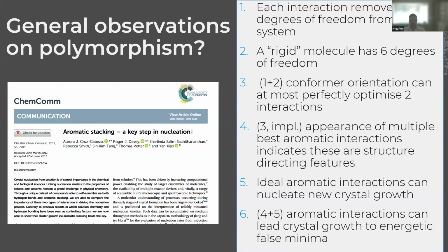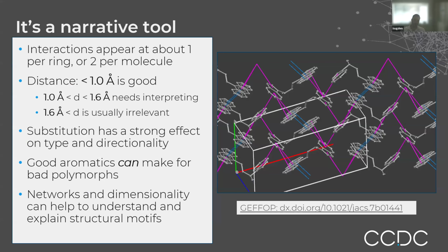I think I will skip over the analysis here, but it was reinforcing the work that was done to produce this prototype. So it's a narrative tool, and it's showing that interactions appear about once per ring or 2 per molecule. Interactions with a distance of less than 1 angstrom from ideal show you it's a good aromatic interaction. There's a range that needs interpreting, and then further than 1.6 angstroms from the ideal position,